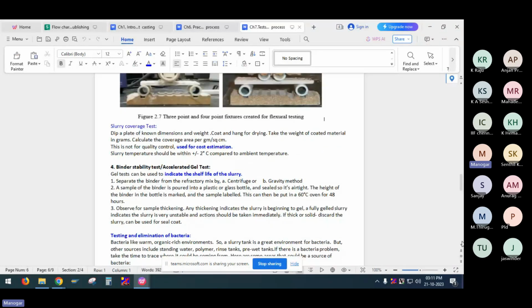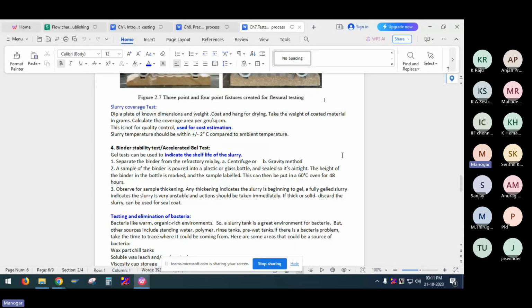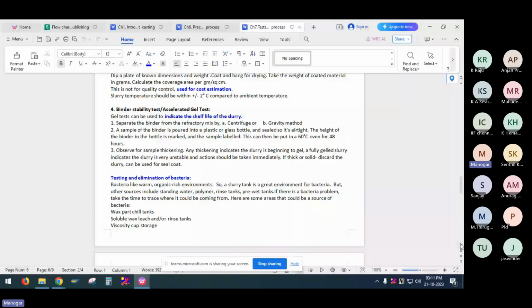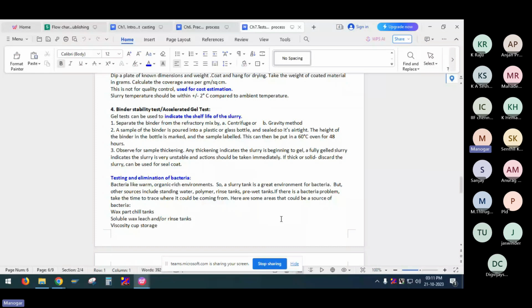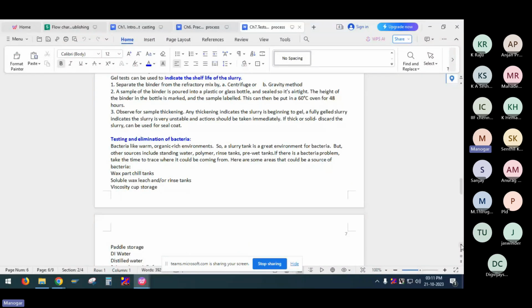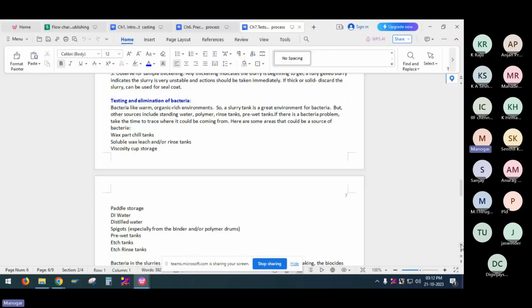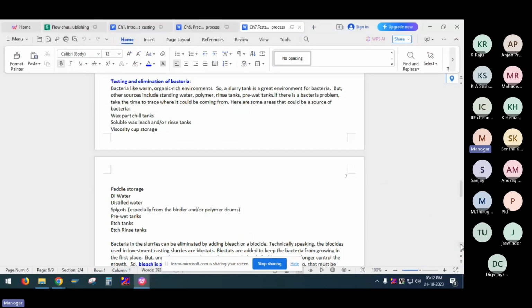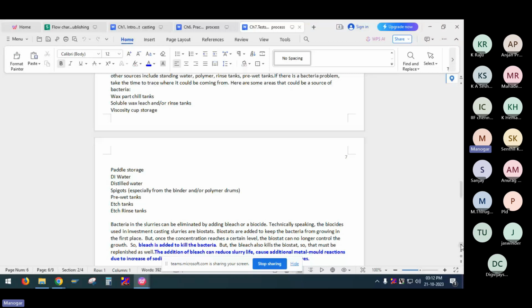Binder shelf test or accelerated gel test. It gives the shelf life or the stability of this binder. The elimination of bacteria. So when the slurry or binder, that is the coating material, is stored after mixing, there is a chance for bacteria pickup and a bad smell will come. So that is to be avoided in slurry storage. So what is the source of bacteria buildup? This is given here. Wax part chill tanks, soluble wax leach, rinse tanks, viscosity cup, paddle storage, DI water, distilled water. Wherever you are using this storage area, these are the sources for bacteria growth.